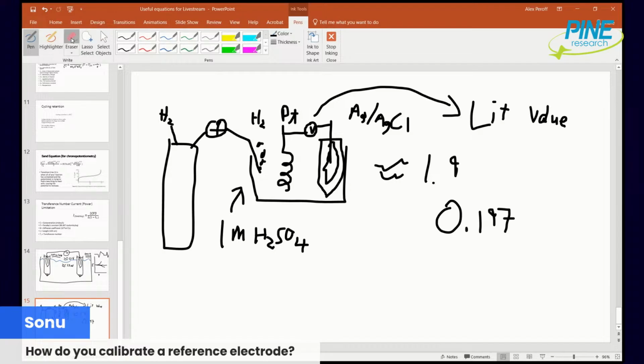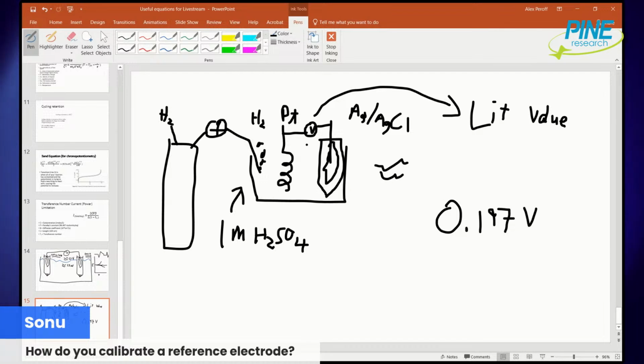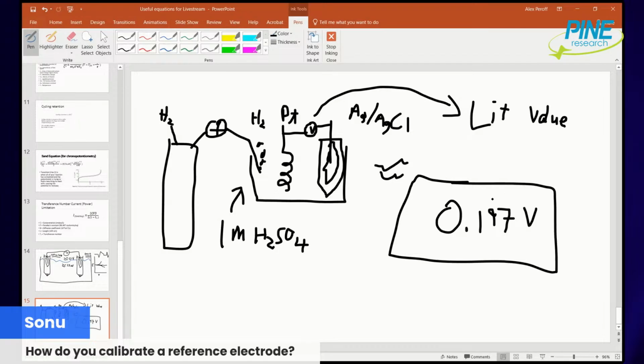It depends on the concentration of Cl, whatever, something like that. So I got 197 millivolts when I looked at the difference. And if I got a negative, I just had to switch the electrode leads. But if I got this value or close enough, like maybe it's 6 or 5, I knew that my reference electrode was correct because it matched the literature value.